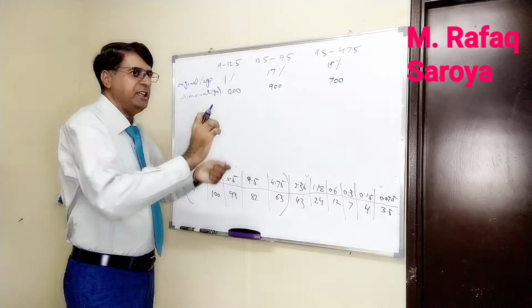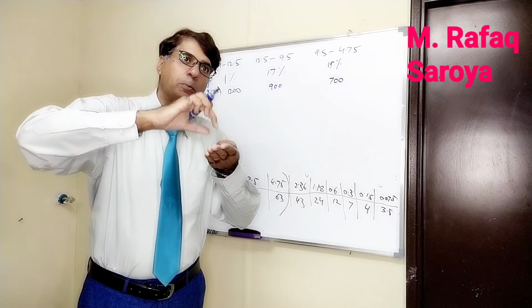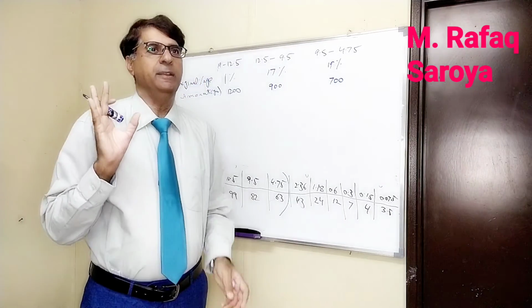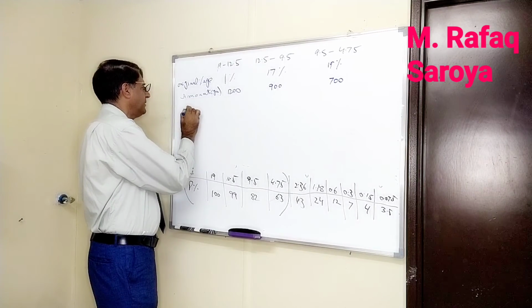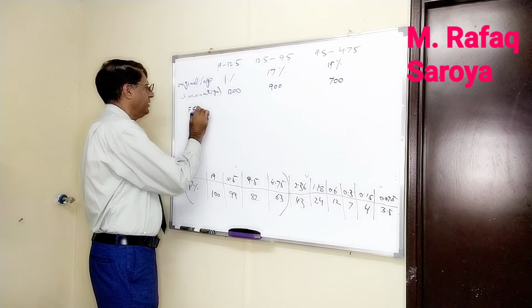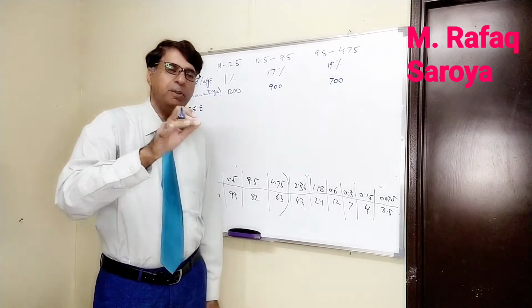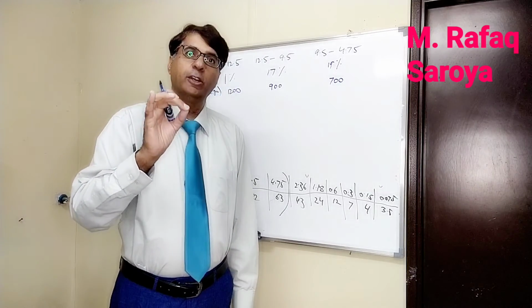When I have taken these representative samples, each particle one by one will be made to pass through points A and B. Here I will see how many particles are flat and elongated, meaning those particles which have passed through point B, which is related to the thickness.